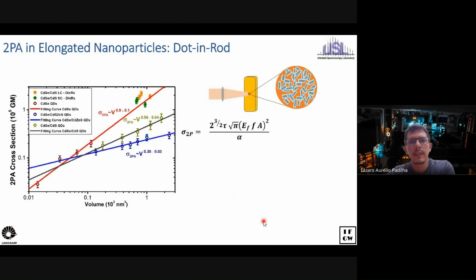To look at these, we have also compared the two-photon absorption as a function of the volume, and put this comparison together with the spherical materials. To do so, we need to rescale the two-photon absorption for nanorods by a factor of 5. And that comes because of the anisotropy of these structures. They are not the same in different directions. If we do so, we see that, in fact, the dot-in-rod structures have higher two-photon absorption cross-section than the spherical core shells. And that probably comes from the fact that you have higher penetration of the electric field.